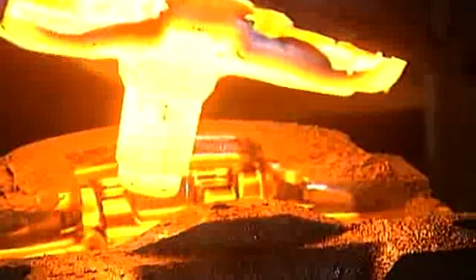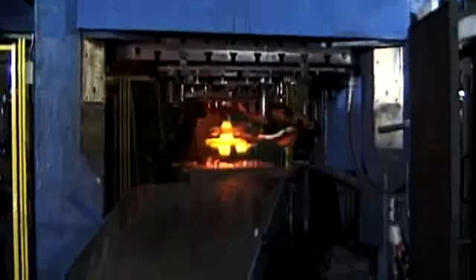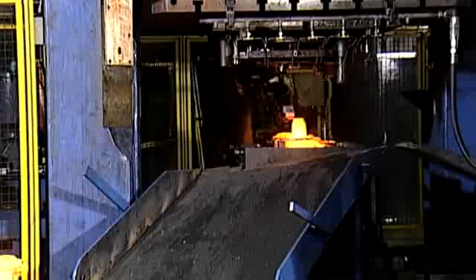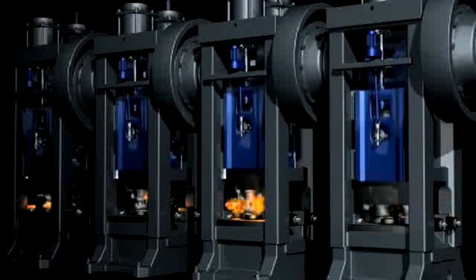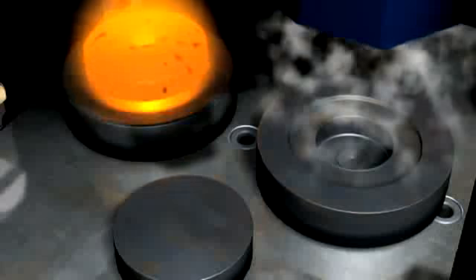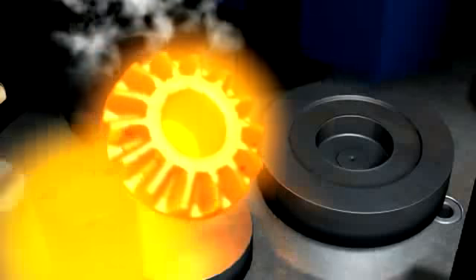Excess material from the rough forging flows into a residual slit between the die halves and forms a ridge, which will subsequently be removed. The reopening die releases a forging with the desired shape. The degree of deformation is limited by a number of factors. Forgings with complex or intricate shapes thus often require several forging steps using sequenced tool sets, each performing a limited portion of the total forming process. The final contour will only be achieved by the last process step.